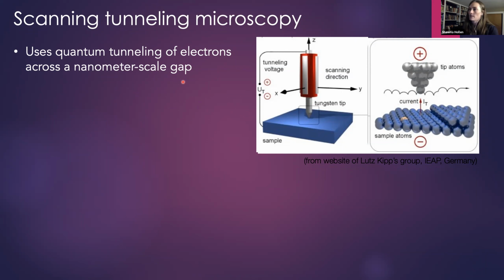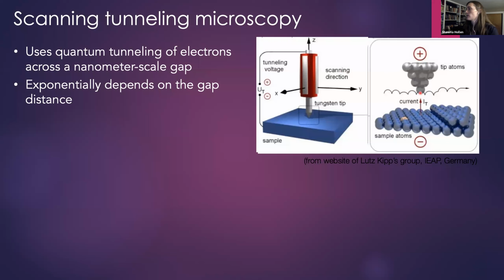So, quantum tunneling across a nanometer scale gap. The probability that an electron will tunnel depends exponentially on the distance between the last atom on the tip and the first atom on the surface. And that means that we're really sensitive to changes in height. So if the tip is over the top of one of these blue atoms, we will get a bigger signal. And if it's in between the blue atoms, we will get a lower signal. So as we move the tip across the surface, it traces out the contours of the atoms on the surface. And that is the mechanism that we use to image atoms.